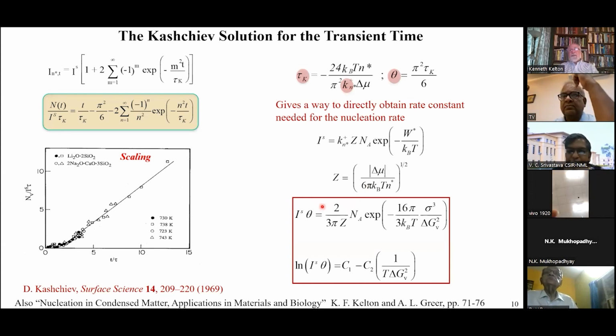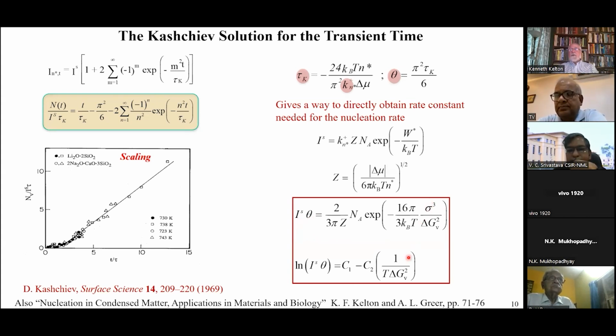And when you do that, it's just a matter of taking these two equations with that one and doing a little bit of algebra. You get to this expression: the steady state nucleation rate multiplied by the induction time, if I plot that as 1 over t delta GV squared, I should get a straight line.